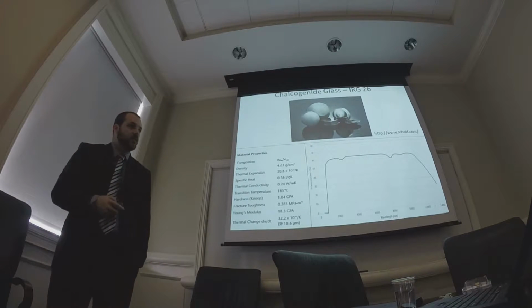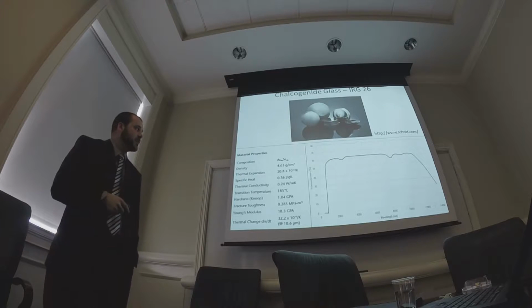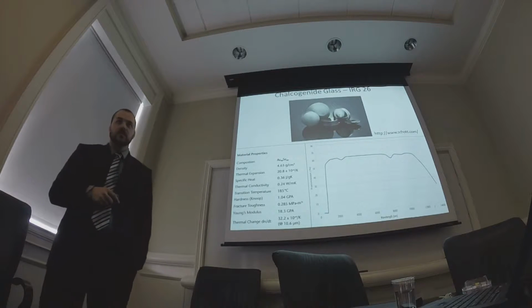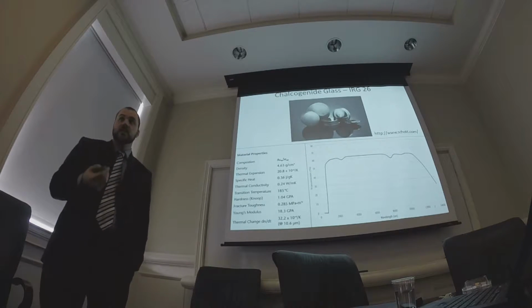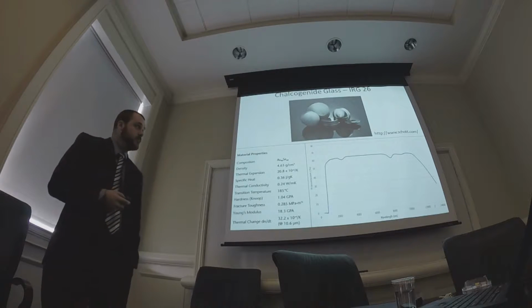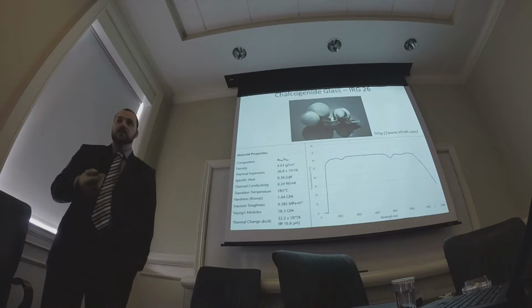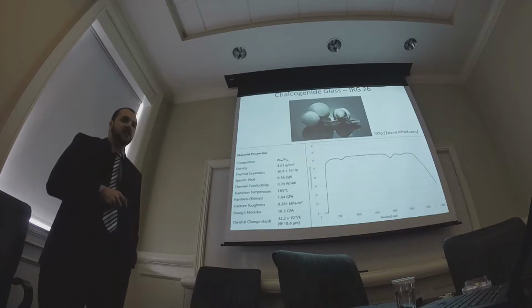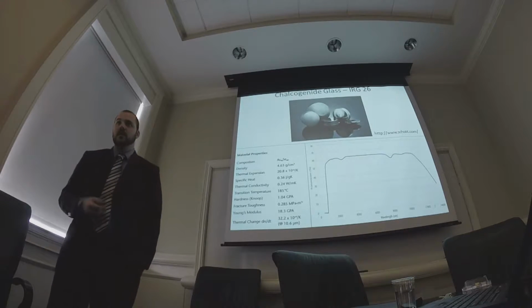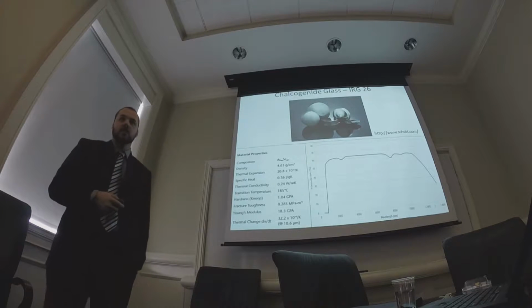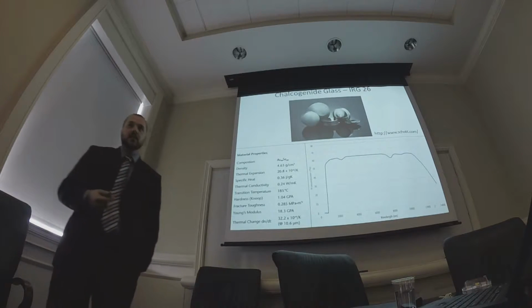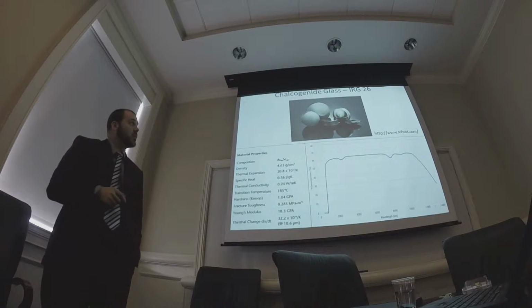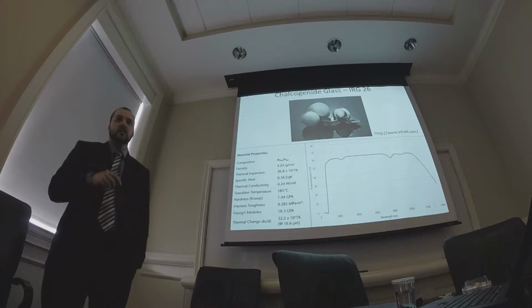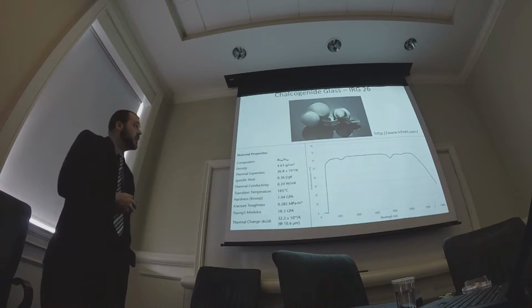Also, the reason why this material was so sought after is the glass transition temperature, the temperature at which the material starts to deform even under its own weight, is 185 degrees Celsius. So this leads to molding capability—can you mold infrared optics as opposed to diamond turning all of them? But we would like to prove this material can be prototyped with diamond machining.